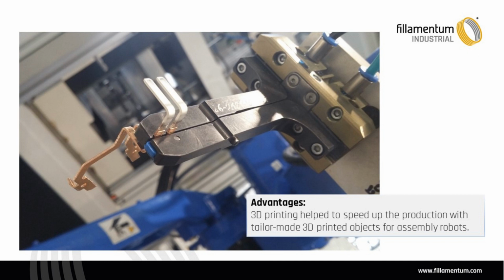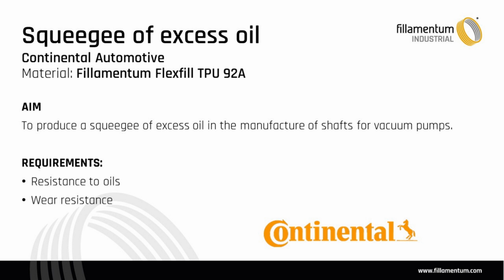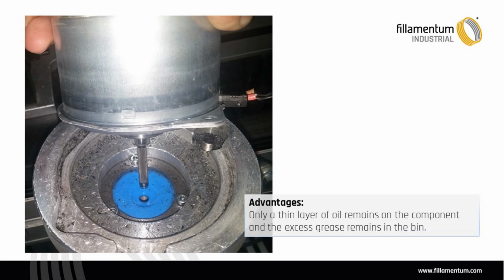And now it's time for the second case from this company, which is about a squeegee for excess oil during the production of electric vacuum pumps. The material used in this case study is the Flexfill TPU 92 Shore A, and the aim is to produce a squeegee for excess oil in the manufacture of shafts for vacuum pumps. The main requirements were oil resistance and wear resistance, because the shafts are dipped into a bin with oil, and the squeegee removes excess oil from the shaft. There are also small fins on the shaft which can damage the squeegee, so the wear resistance is also important.